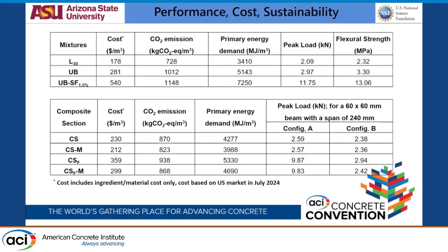So we see there's a cost reduction of around 40% on the fiber CSM. That's around $300 from a 540. The thing we should remember is that it's just a 15 to 20% loss on the strength, while for carbon dioxide, we are getting another 20-30% decrease in the carbon dioxide emission.